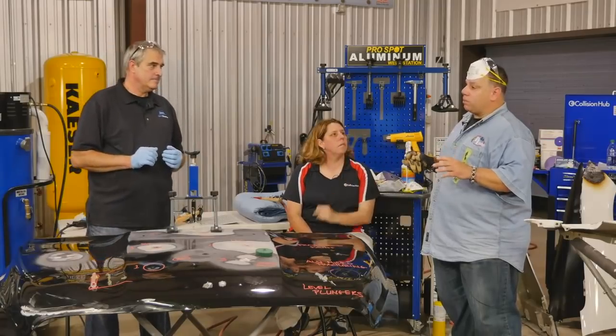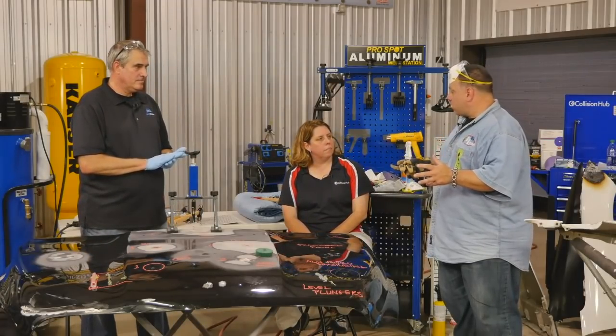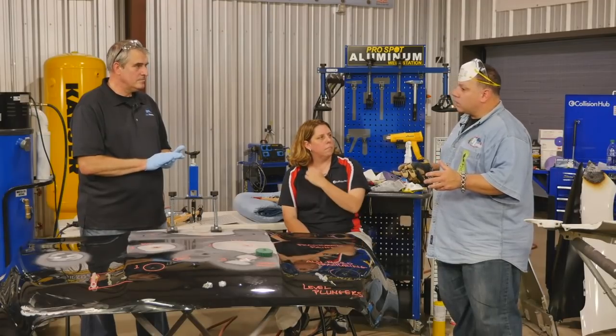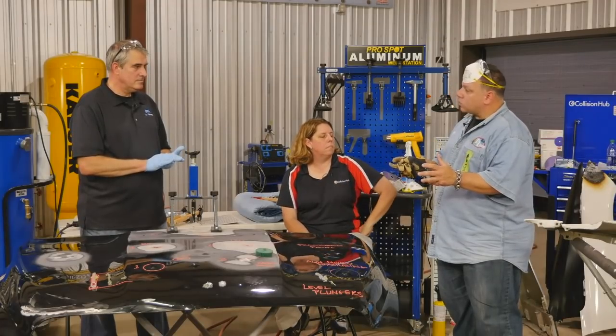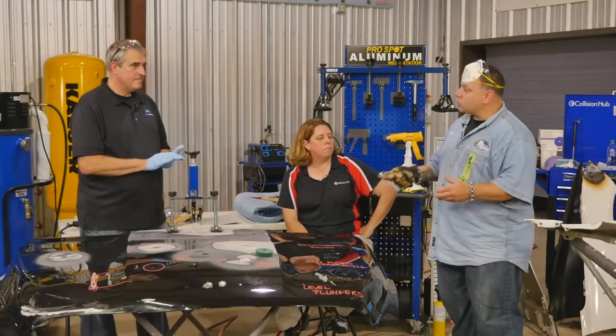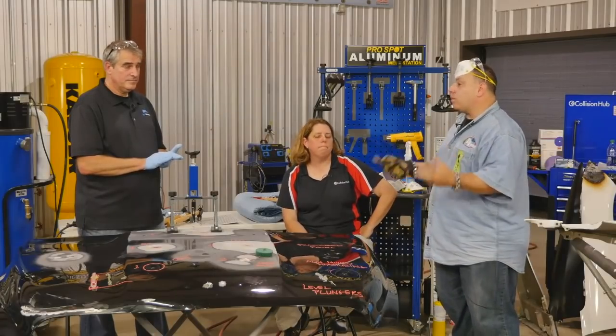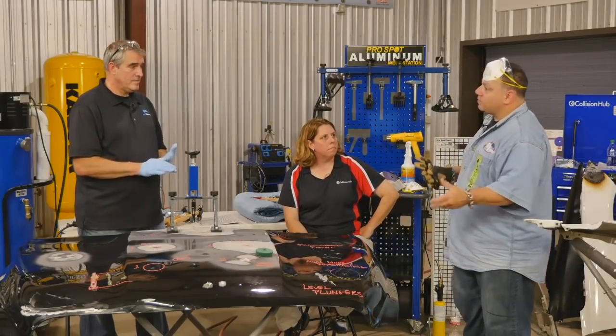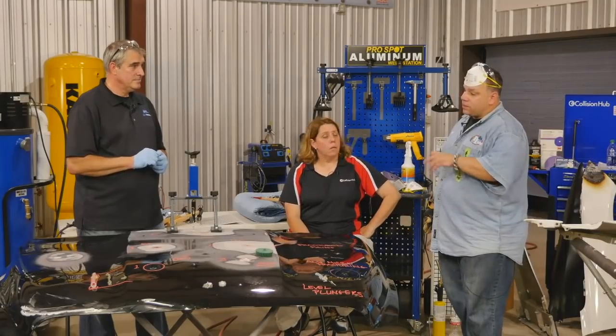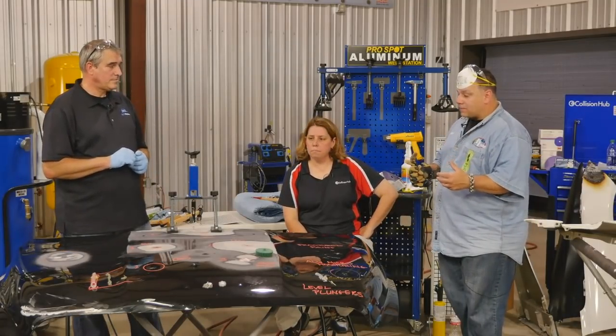These are just steel hammers — can I use these on the aluminum hood and then go use them on the steel fender? No. Just like I can't use this roll-lock disc on aluminum and then go use it on steel. I can't use these 100-grit roll-lock grinding discs on aluminum and then on steel. The material gets embedded and you can transfer that contamination. You shouldn't even use the same sanders, because they've got a ton of dust jammed in them. We need a separate set of hammers, a separate set of DAs — a separate set of everything for aluminum. And buy a standard set of metric tools just to take things apart in that area.